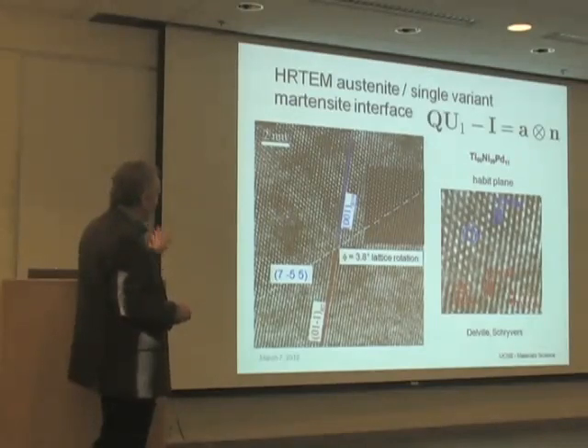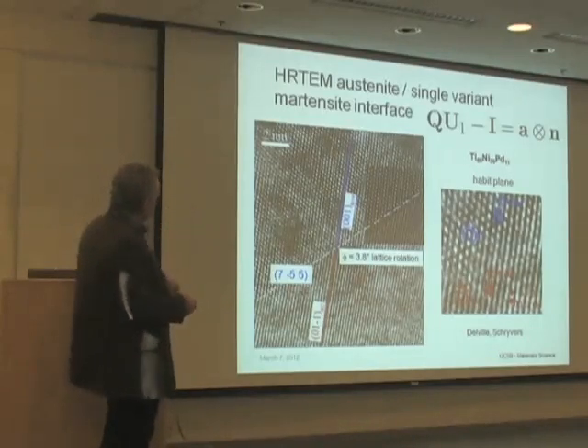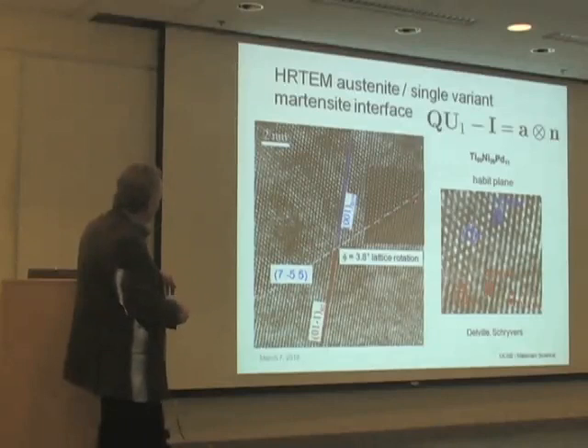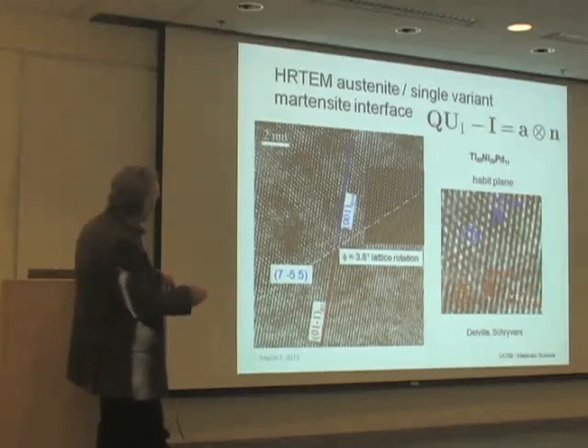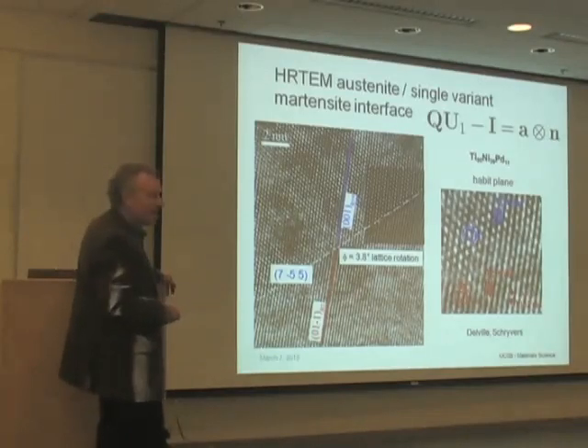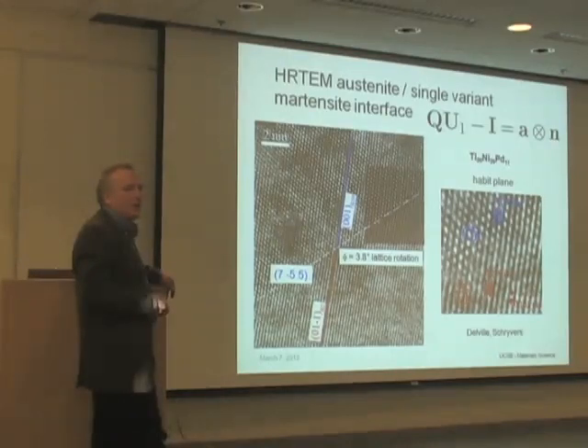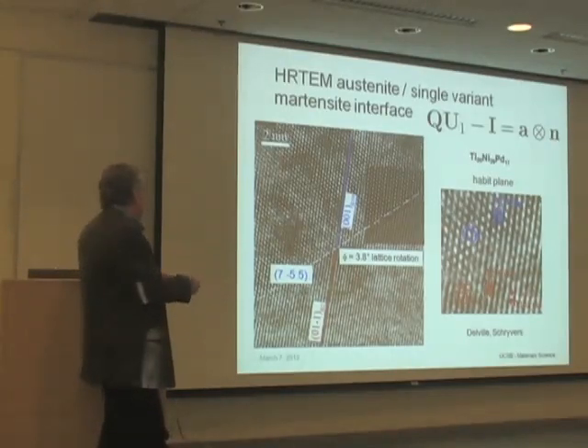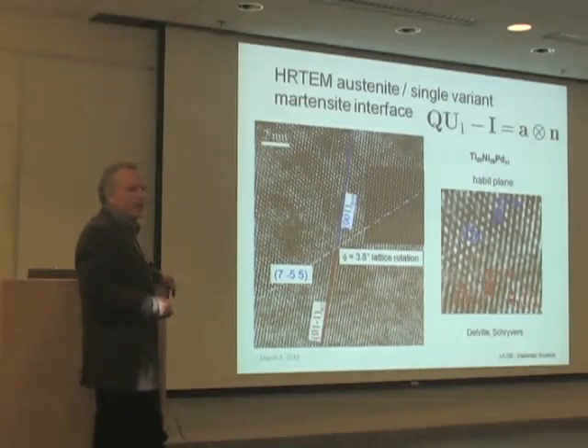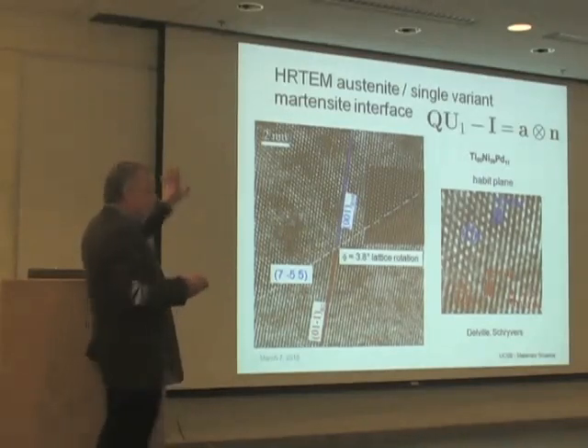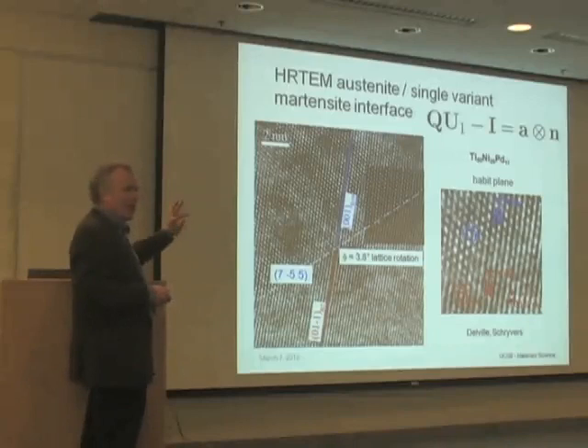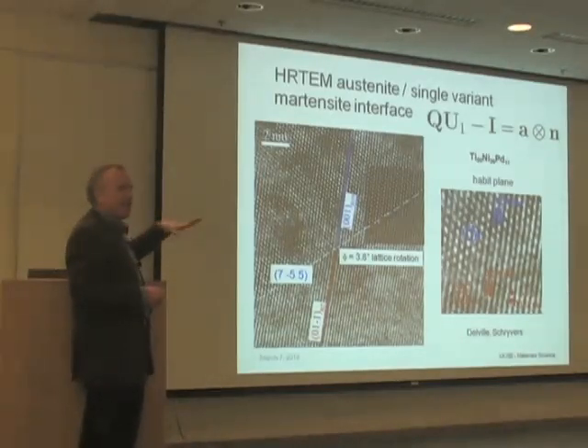And in any case, in that alloy, at high resolution, you see perfect interfaces between austenite and martensite. They have normal (7 -5 5), that's that n. The angle phi you can measure between lattice planes here, that's actually the angle in this rotation matrix Q. And so everything nicely agrees in that picture with the compatibility condition between the austenite and the martensite. And actually, the whole microstructure changes. It gets much simpler. There's many interfaces between austenite and martensite. It's quite different from the other case.